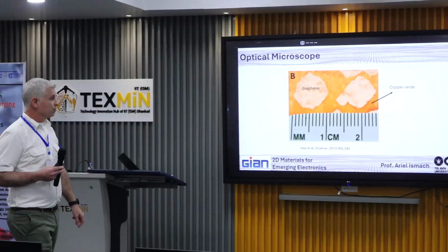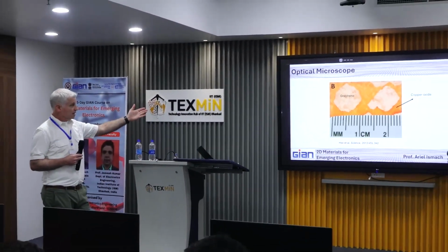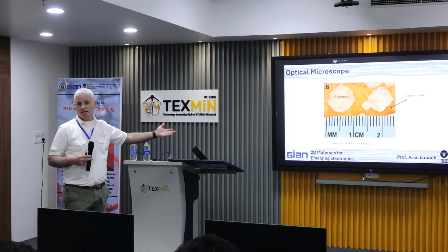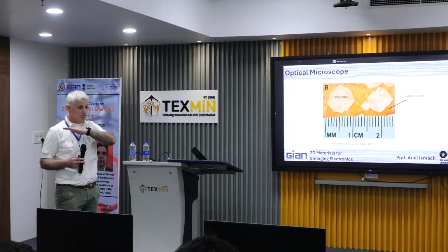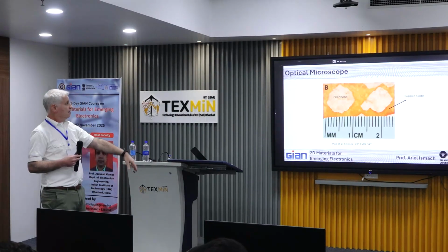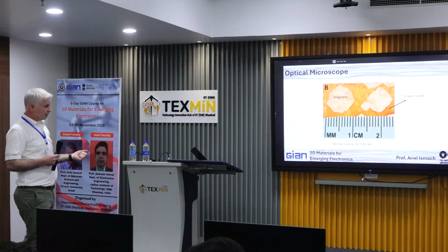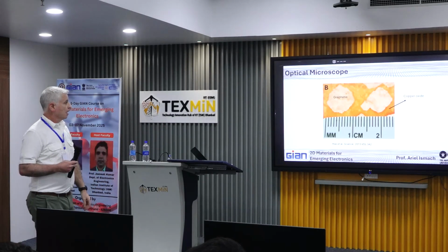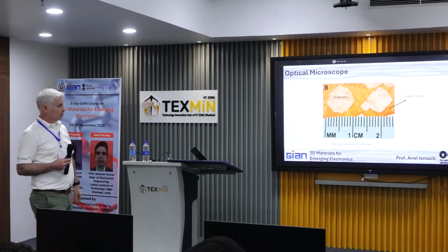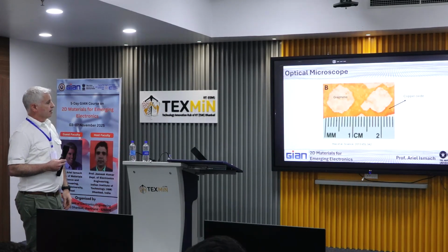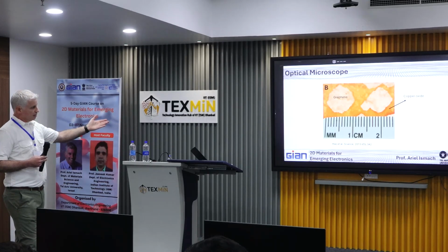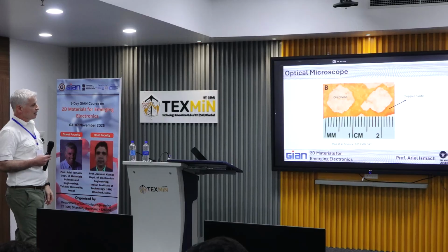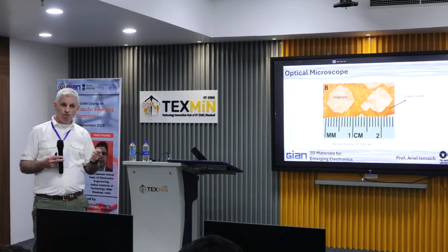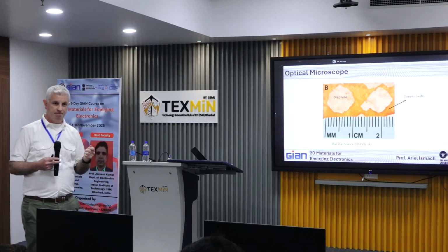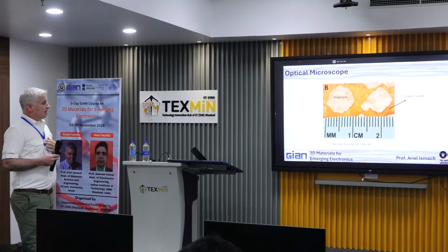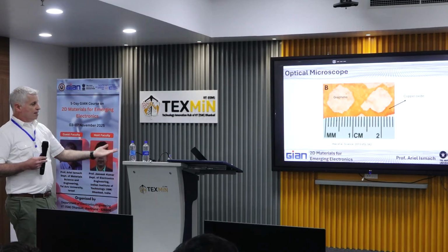So what information can you take from this? First of all, this is what is called a sub-monolayer, right? There is no full layer, you have isolated domains. The domains are very clean, about a millimeter, and apparently single crystal, although you need to check this by other methods. So you can check by this simple optical microscope, but you need to know your material, you need to know your sample, and by that you can check the coverage very fast.